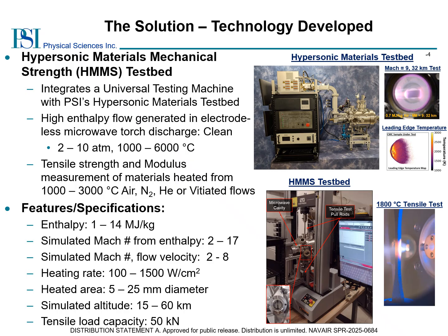PSI has demonstrated tensile strength and modulus measurements of a range of materials heated from 1000 to 3000 Celsius in air, nitrogen, helium, or vitiated combustion flows in the testbed. The image next to the HMMS testbed shows a carbon-carbon composite dog bone heated to 1800 Celsius during recent tensile testing in the testbed.